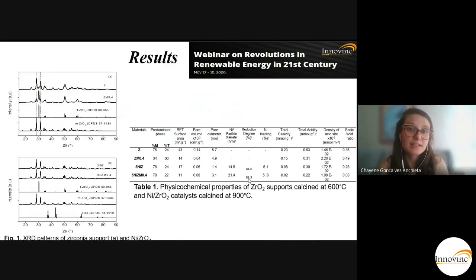And now I'm going to show you the results of this article. Initially, we did X-ray diffraction of the synthesized zirconia supports. We used ionic liquid at different concentrations to obtain different crystalline phases. So we have to do some thermal treatment to obtain the support, and after impregnating nickel particles over the support, we need to calcinate the catalysts again. What we have seen by X-ray diffraction is that we have different phase compositions related to the support synthesized with or without ionic liquid.